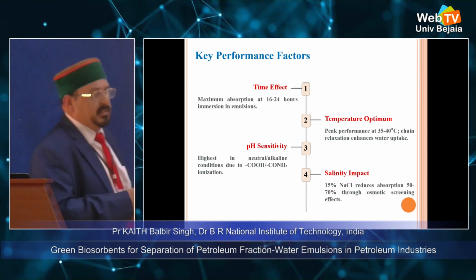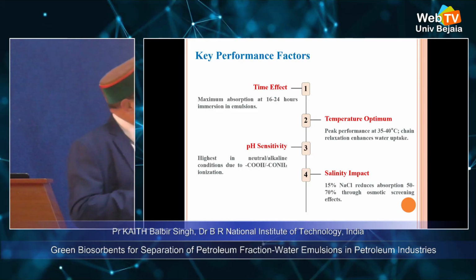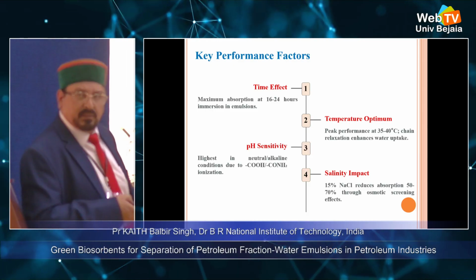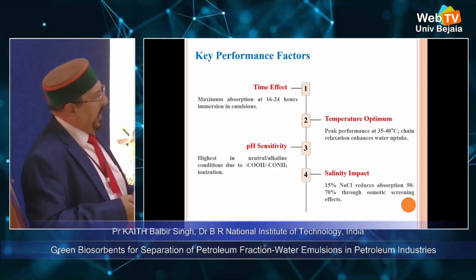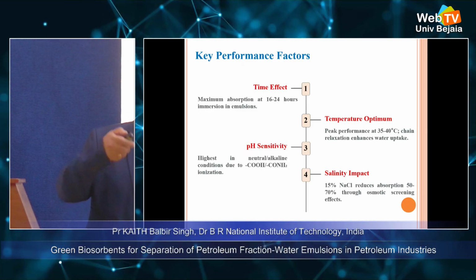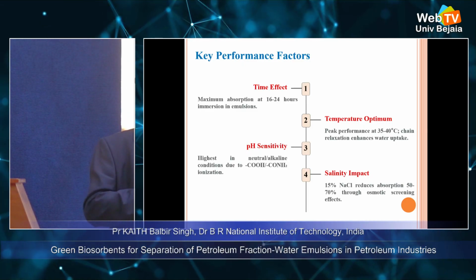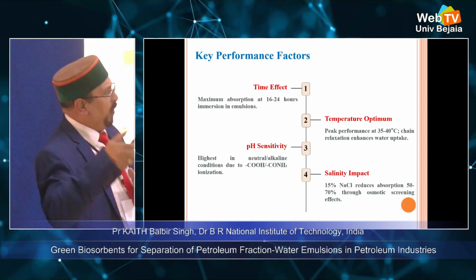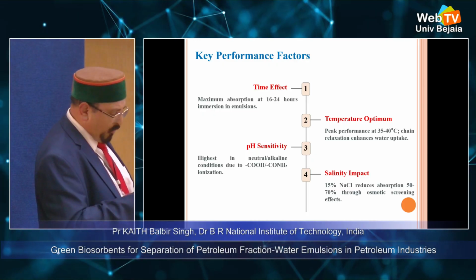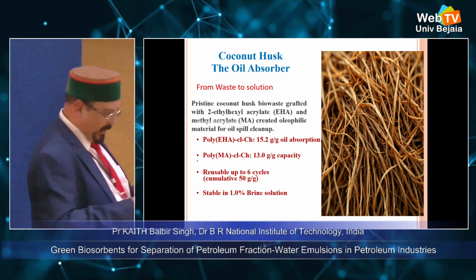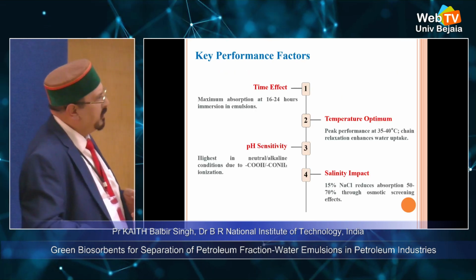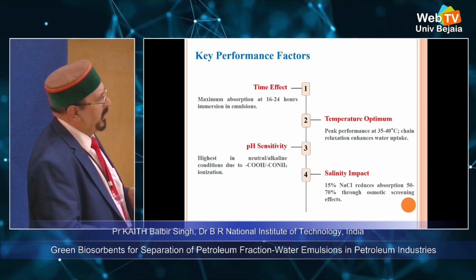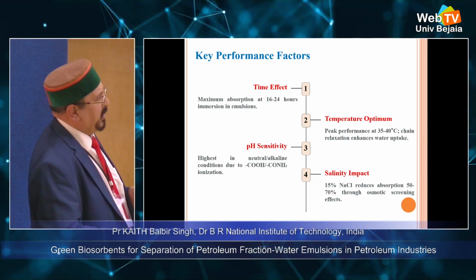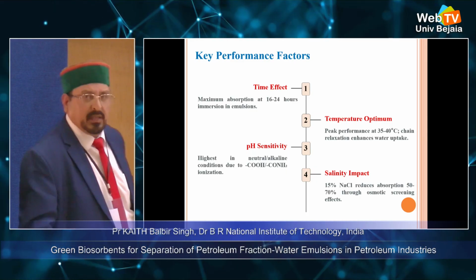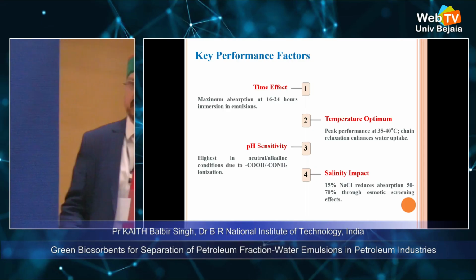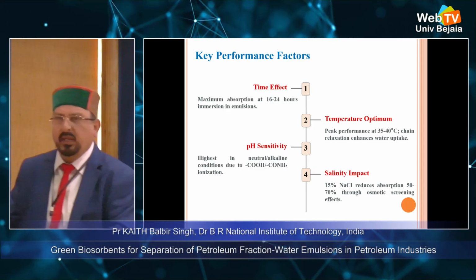The key performance factors here were time effect, temperature optimization, pH sensitivity, and salinity impact on the separation of petroleum fraction oil and water emulsions. And we found that the efficiency decreased by 50 to 70% when we used 15% NaCl solution, where the efficiency was totally decreased.